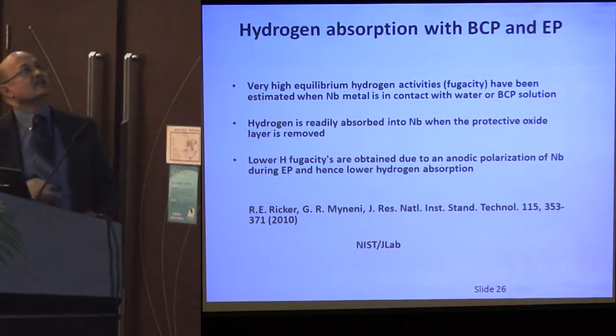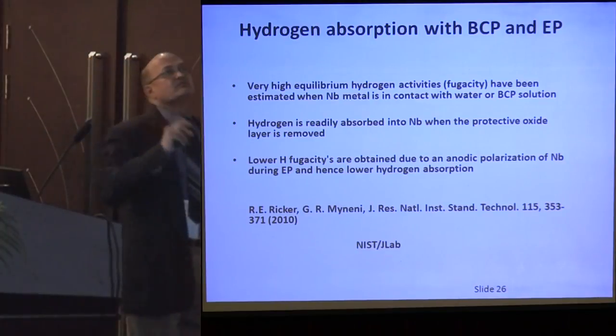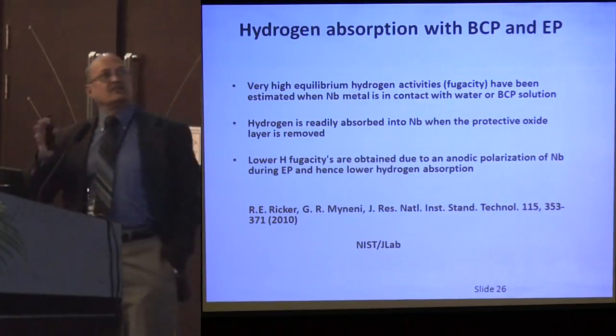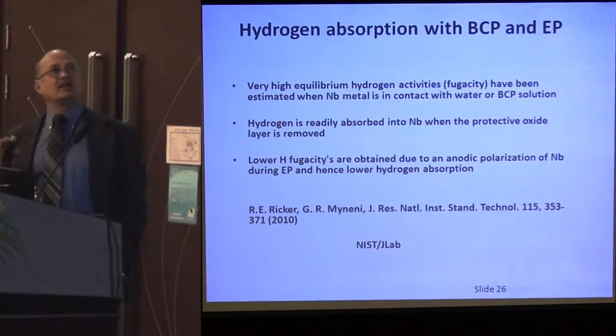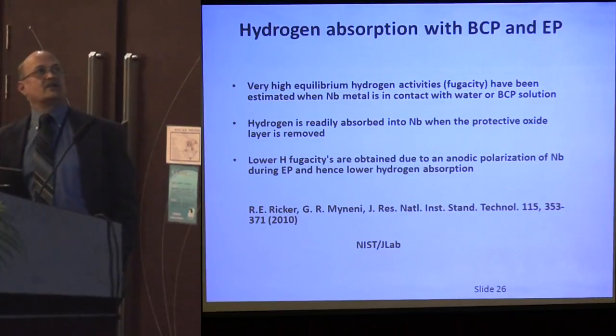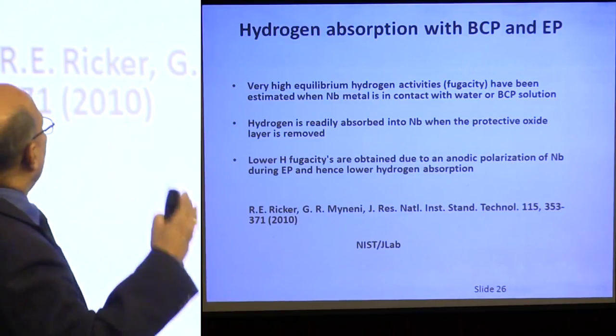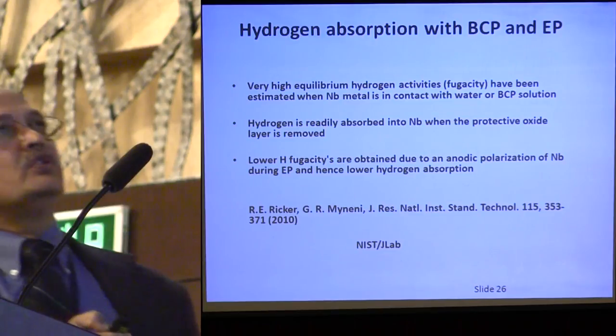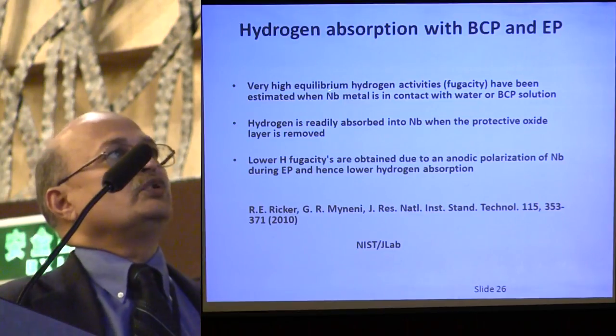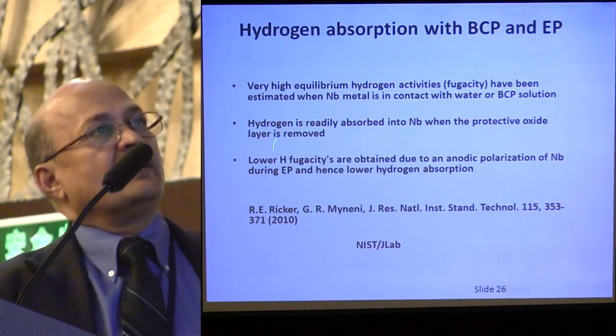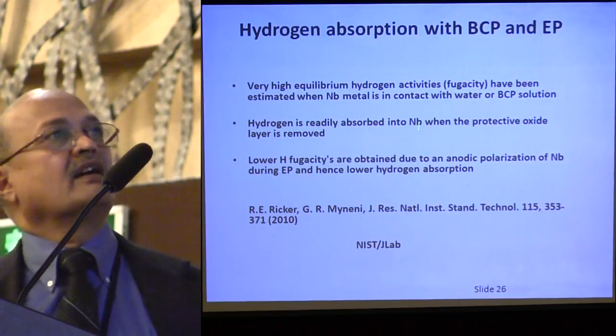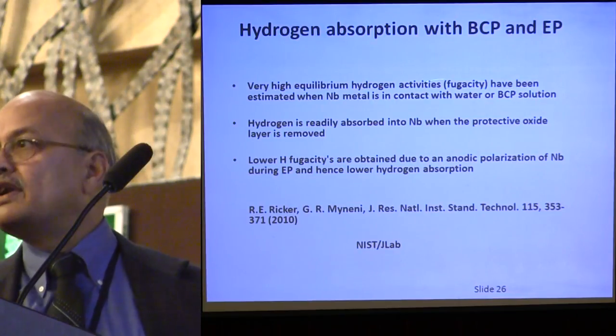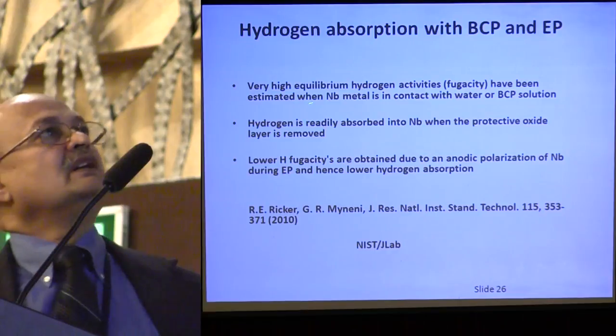I'll skip this. There are two different kinds of processes that are used. One is a buffered chemical polish to remove the damage layer, and the second one is electropolish. Depending on which one you use and depending on the type of niobium you use, you have different amounts of hydrogen contamination on the surface that will determine the performance.